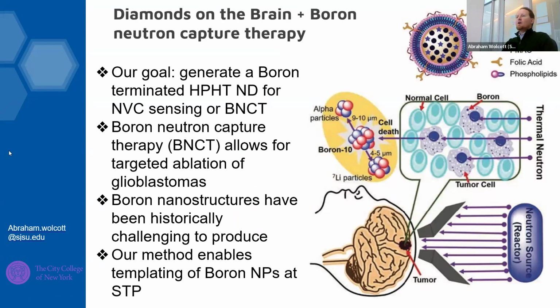But why do we care? Well, what's interesting is that if we can put boron on the surface, we could use it not only for NV sensing, but also for boron neutron capture therapy. Boron neutron capture therapy is a way of treating glioblastomas, highly aggressive brain cancers that can't be treated any other way. And so boron clusters are injected into the brain, and then you irradiate the patient with neutrons. The neutrons are only captured by boron-10. There is literally a nuclear reaction which generates lithium-7 and alpha particles.